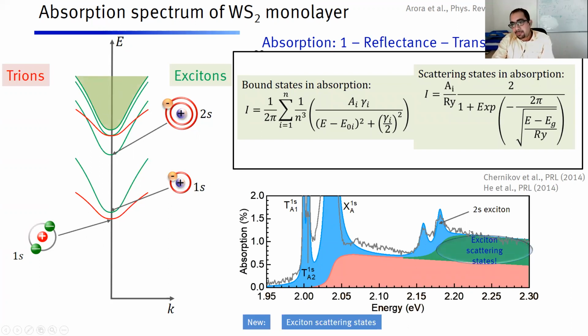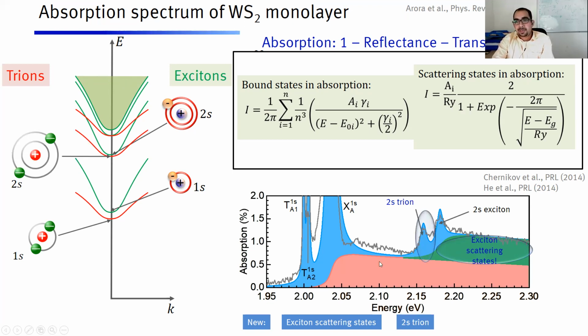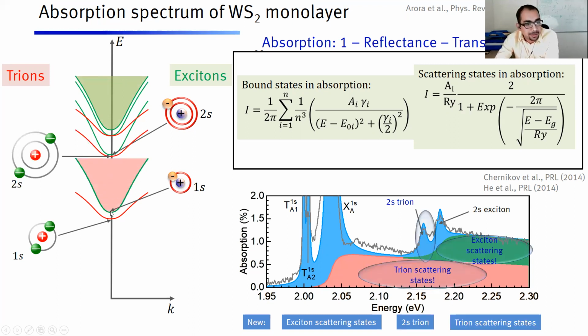They start from the band edge. After the band edge is somewhere there. And then we expect an excited state of trion, which is visible here. This is a doubly excited state of trion. It's visible here as a peak. But so far we have just identified this by looking at it. But we need to find evidence if this is the excited state of trion or not. And then there is another step-like thing which should start at the energy position of the exciton, and this should be the trion's scattering state. All right. So we have seen many new things, all those things which we had predicted in our spectra, but still we have to give evidence.